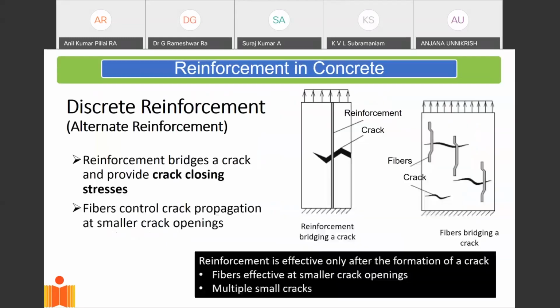So now what we're looking at is discrete reinforcement. So instead of having conventional steel reinforcement bars, can we start looking at the same steel provided in the form of fibers? The advantage again is if I have a steel bar that is placed inside concrete, the steel bar is not effective till the crack comes and intersects the steel bar. So that means the crack has to form, and it only encounters resistance once it crosses the steel bar. Whereas if I take the same steel bar, chop it up into smaller fibers, then every time a small crack forms inside the concrete, it is locally arrested.